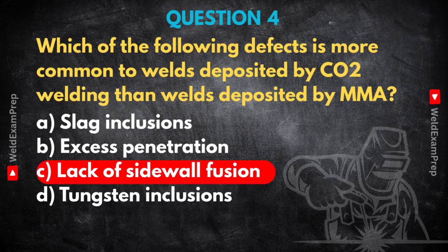It can be, yes. Sometimes it's quite obvious, like a clear groove along the weld toe, but other times, especially if it's intermittent or just below the surface, it might look okay visually, but the fusion just isn't there underneath. That's why understanding the process, knowing where to look, and sometimes relying on NDT methods like UT or radiography is so important for ensuring weld integrity, especially for critical applications. You can't just assume it's okay because the surface looks smooth.